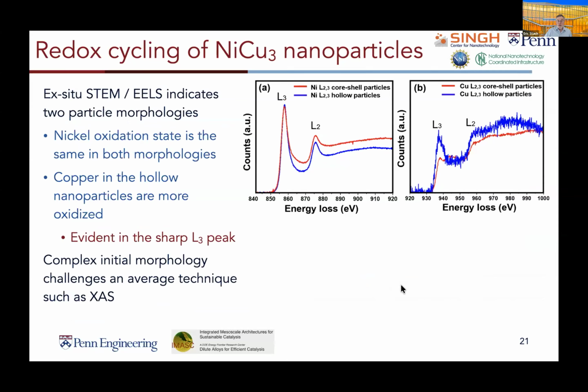So again, we can use EELS, right? It turns out that EELS, this is ex situ, so before any reduction or oxidation, is again consistent with this. The nickel is oxidized in more or less the same state in both particles.